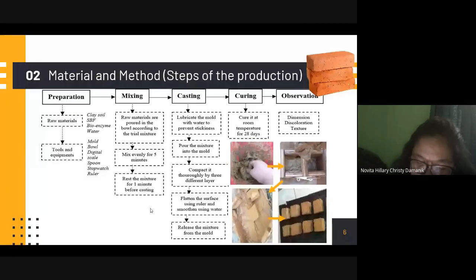So after all the materials are ready, here are the steps of the production. The first one is preparation, and then mixing, casting, curing, and observation. In the mixing part, the raw materials are poured into a bowl according to the trial mixture, and then mixed evenly for 5 minutes into a homogeneous mixture, and then rest the mixture for 1 minute before casting.